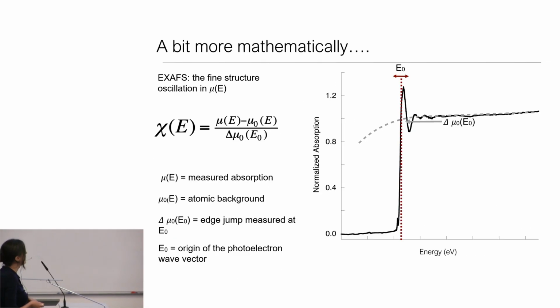Okay, but once we actually do this subtraction, so this is just to show you that we're basically modeling, we have the measured mu of E, we subtract our spline, which is mu naught of E, and then normally at the E0 point, we divide by an edge jump. And we do this because in X-ray absorption measurements, it's very hard for us to measure a true extinction coefficient like you would in optical. And so it's much easier for us to just normalize everything to 1 unit photoabsorber. And so that's normally what we do.